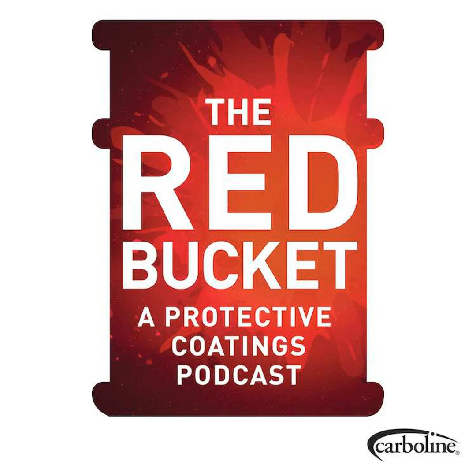The outermost layers of zinc actually do get exposed to the atmosphere because, unlike in a zinc-rich epoxy system, where the epoxy resin is covering a lot of the zinc, not all of it, but some of it, you actually have really good permeability of the atmosphere through that silicate resin system. And so that zinc that's in there is able to oxidize and form those zinc carbonates. But the zinc carbonate salts, they fill in the pores within the film. So you actually are forming a barrier in this rock-like matrix, and you're holding the salts in a little bit better.